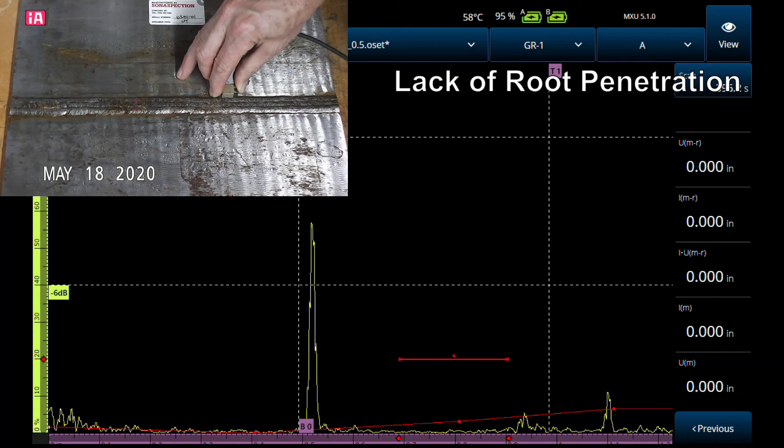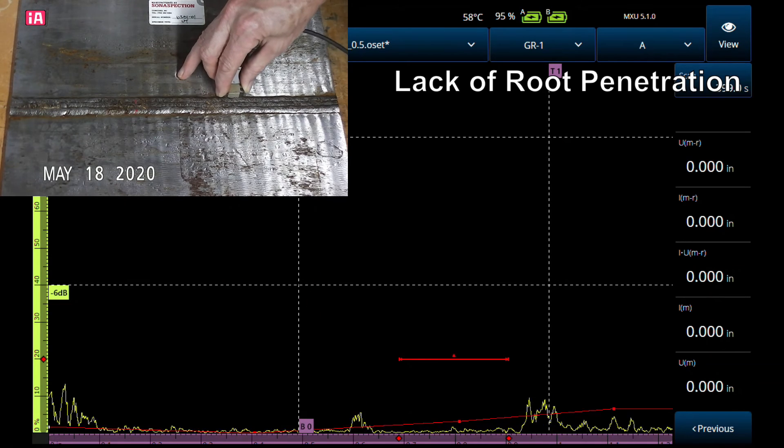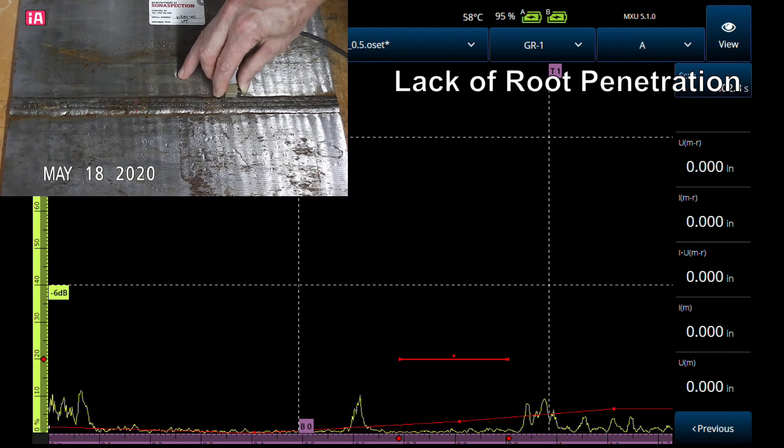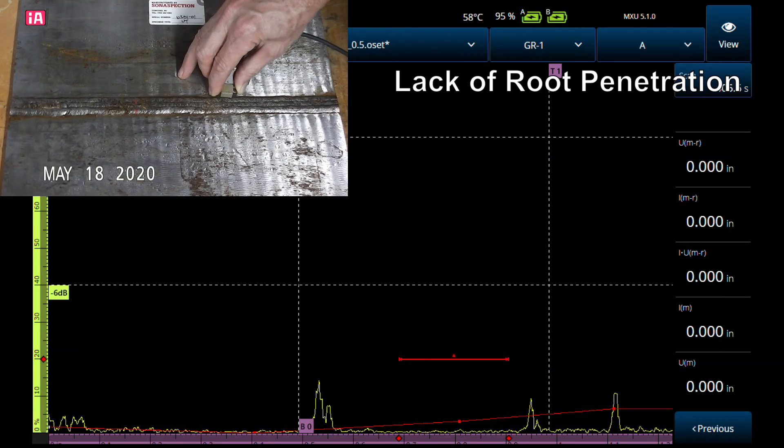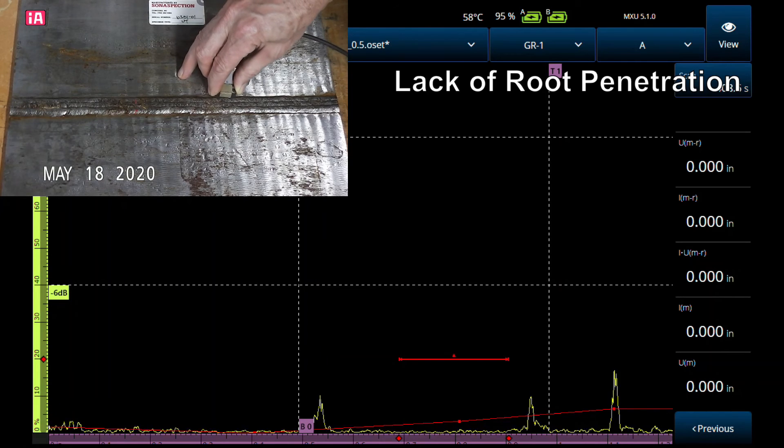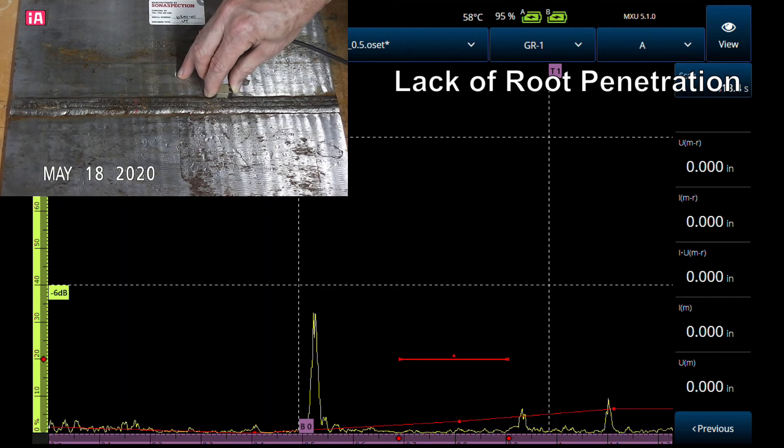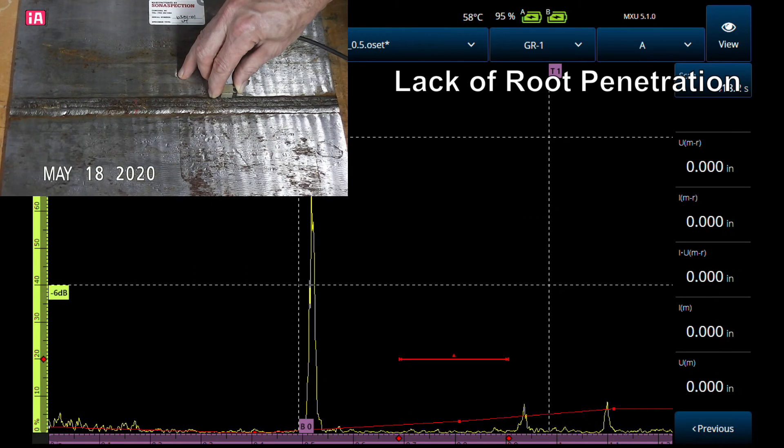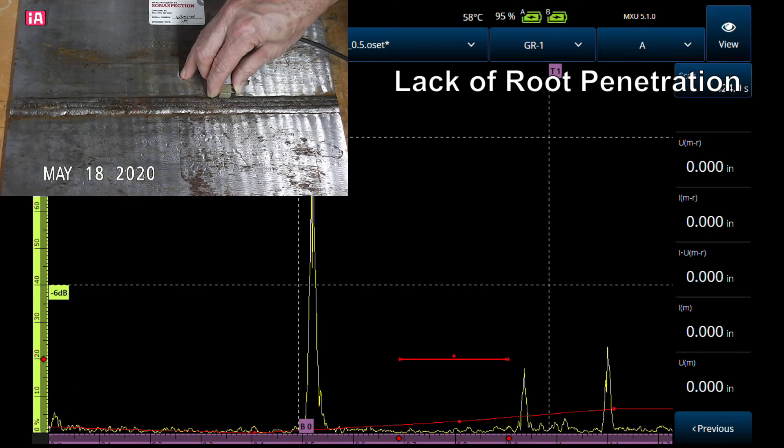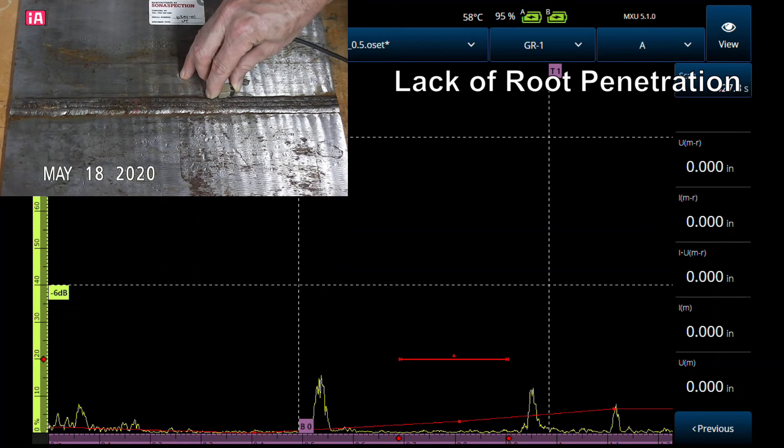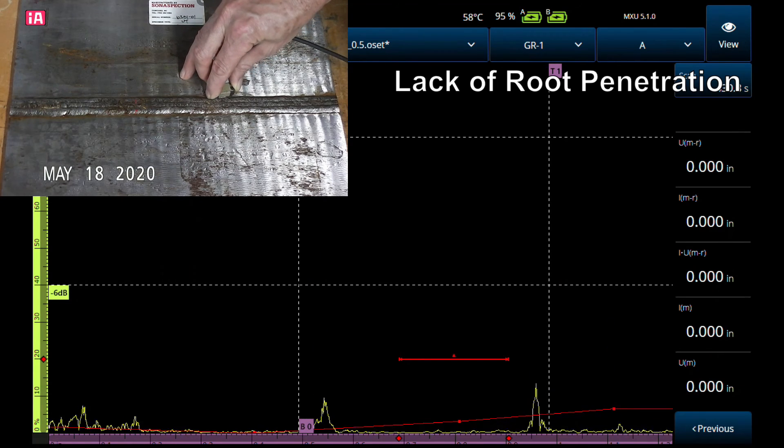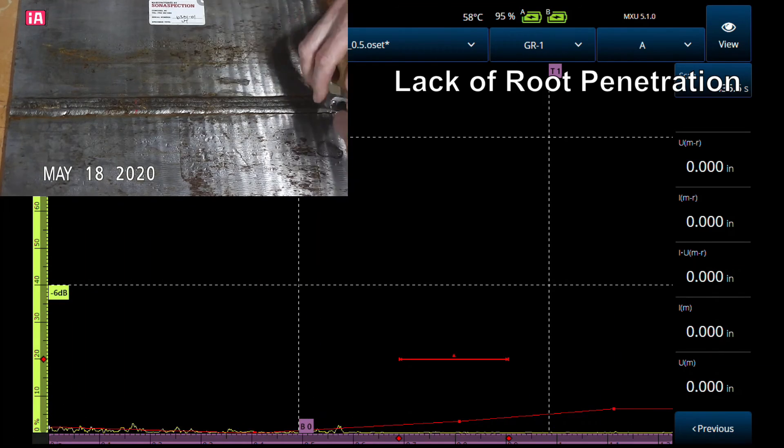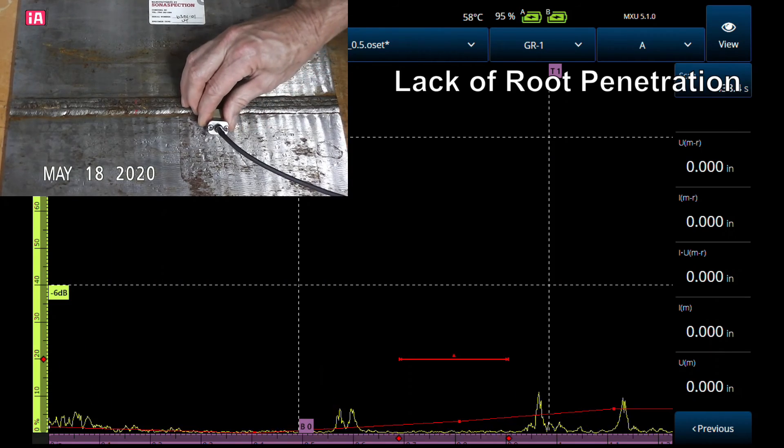You can see it comes in very strong. Let's reduce that down to reference. This can be difficult to discriminate between this and root cracks, which really doesn't matter because they're both planar flaws, both in the root, they're both subject to the same acceptance criteria. So there's no test out there I know that's going to ding you if you call a crack lack of fusion or vice versa or lack of penetration. But usually lack of root penetration has a wide base to the A-scan signal. It's definitely not a smooth reflector. You can skew it a bit and it stays on there, high in amplitude.